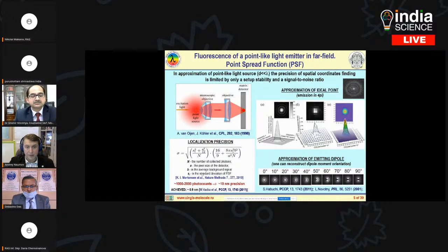And you can see that if you collect about a few thousands of photons from such an emitter, you can resolve the position with accuracy about 10 nanometers without any electronic microscope, without synchrotron radiation. You can find the position of this molecule with accuracy up to a few nanometers. The best values which people achieve in experiments are a few angstrom. In this paper, people succeeded with accuracy about 9 angstrom. And in our measurements, we achieved accuracy up to 5 angstrom.